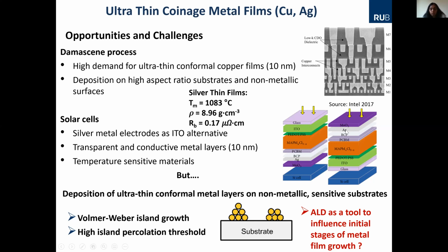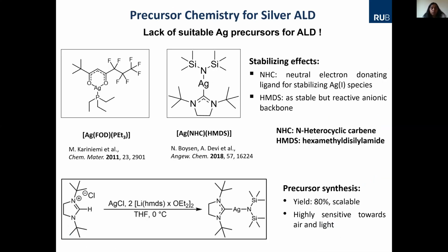So now, what is the challenge for the industry or for the researchers? Whether we can grow silver by ALD. So far, if you look into the literature, there is only one precursor available for ALD or CVD of silver that is working. I mean, it's a working precursor. There may be several silver precursors, but whether it is working for ALD effectively or CVD, we don't know. But then it was shown that this precursor is commercially available and you can buy it and use it.